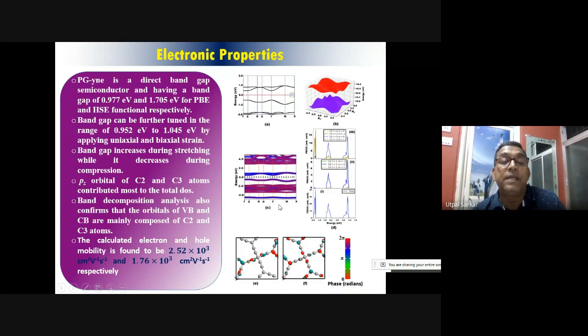The electronic properties are very interesting. For this particular material, we have calculated the mobilities of electrons and holes, and it is found that the electron and hole mobility is very large for this material. And we have done these calculations using the hybrid functional HSE, which is time consuming.